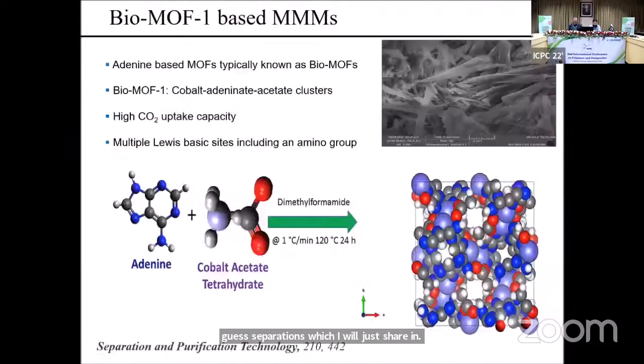Another material that we focused our work on was bio-MOF. Bio-MOF derives its name from an adenine based linker. Adenine is produced from purine, so it's a natural source. That's why the name bio-MOF. It's a cobalt based MOF that has shown in adsorption studies very high CO2 uptake, leading to multiple Lewis basic sites, and as a result CO2 can act as a Lewis acid, and we can have good interactions between CO2 molecules and these bio-MOF molecules. We were able to produce very nice flake shaped bio-MOF crystals which showed very high crystallinity,